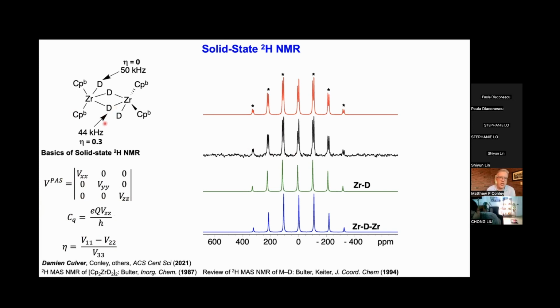So for bridging zirconium deuterides, we have small quadrupolar coupling constants and eta greater than 0, which is exactly what we expect based on this review by Leslie Butler. And the terminal zirconium deuterides have characteristic chemical shifts as well. Or I'm sorry, quadrupolar coupling constants as well.